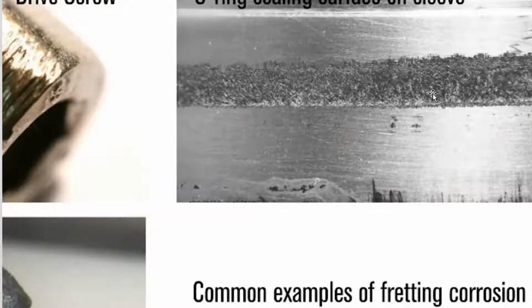A lot of these studies that I found are on prosthetic implants, like hip replacements, shoulder, ankle replacements, where you might have stainless steel on stainless steel, and it's lubricated by the meniscal juice, whatever that's called. Also albumin, which is a cell transport fluid, and even still they get fretting corrosion. So yeah, pretty interesting. That's why a lot of those now are titanium, or they'll be coated with some sort of polymer, and that's to avoid fretting corrosion.